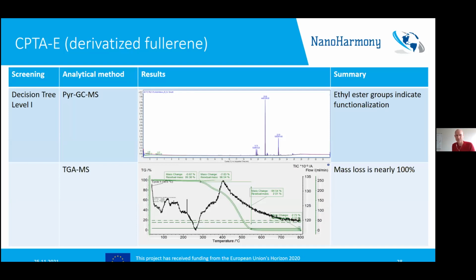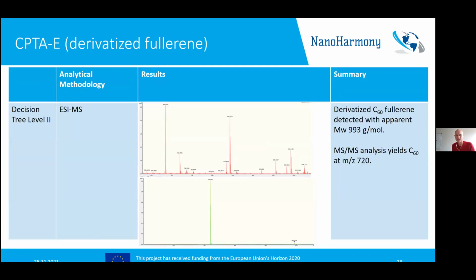We could also get some information with pyrolysis GC-MS, and finally by direct infusion electrospray ionization MS, we could see a molecular ion of the functionalized fullerene, and when we applied tandem mass spectrometry to this compound, we would yield the original fullerene structure, which indicates that the side groups were torn off using electrospray ionization.